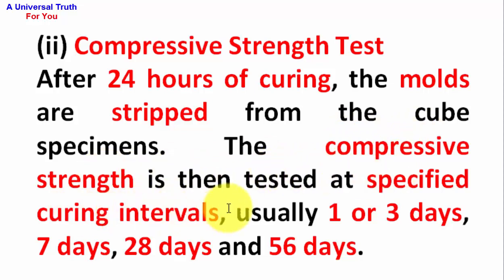The compressive strength is then tested at specified curing intervals, usually 1 or 3 days, 7 days, 28 days, and 56 days.